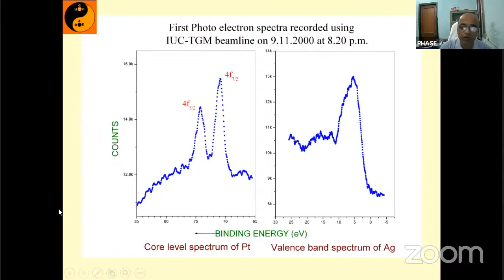Normally in the laboratory, you will require 1 or 2 hours to generate this kind of spectrum, because you have to do continuous scanning of this energy range, as the intensity of the source is very low. Here you can generate the spectrum within 5 minutes. This way one can save time and generate a very good quality spectrum.